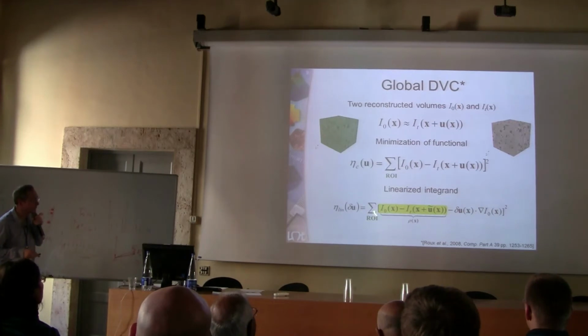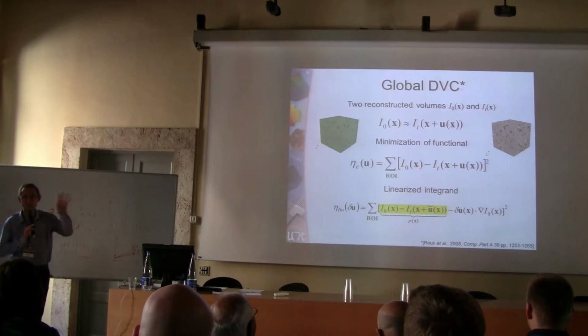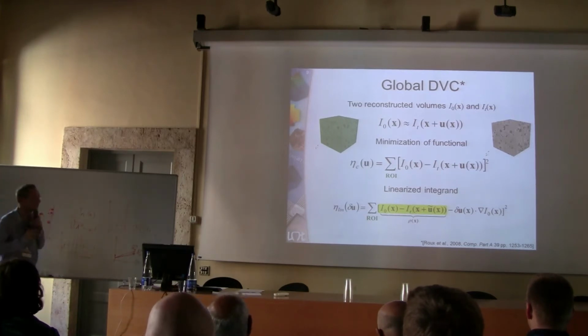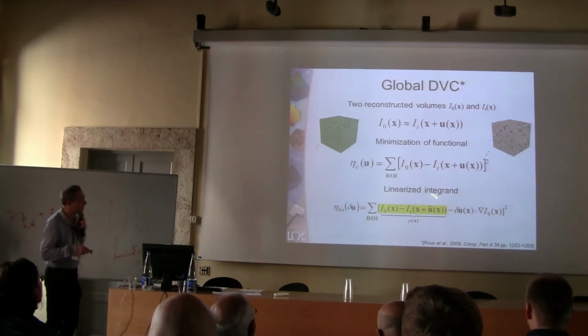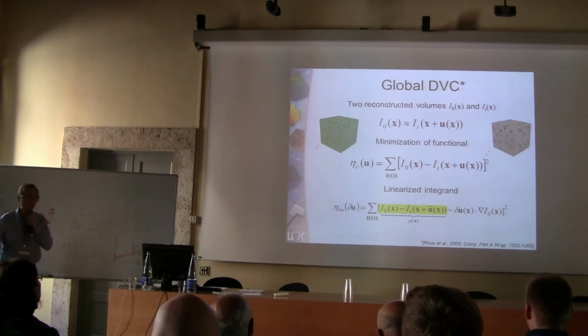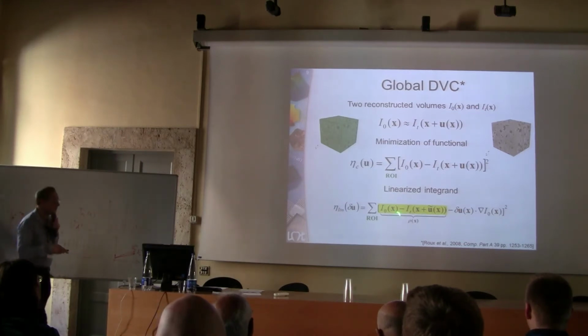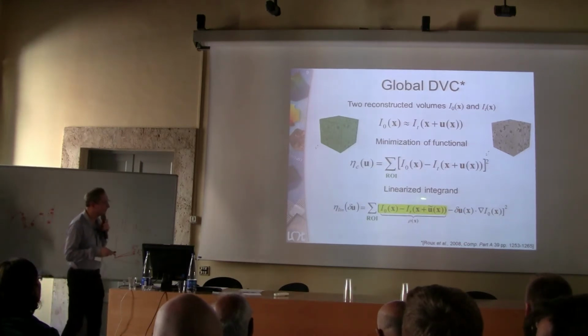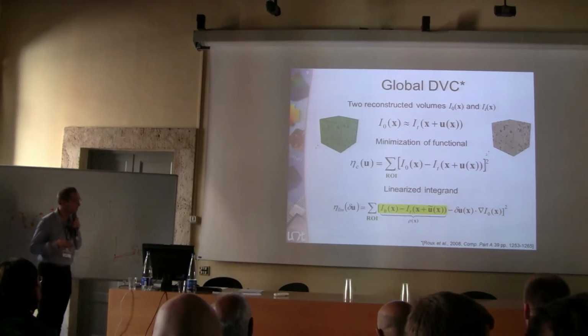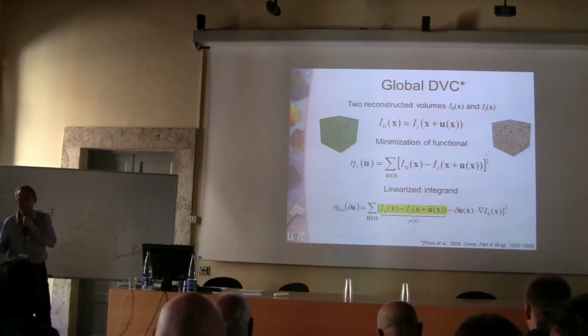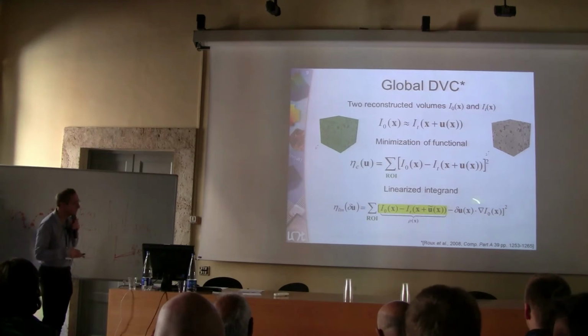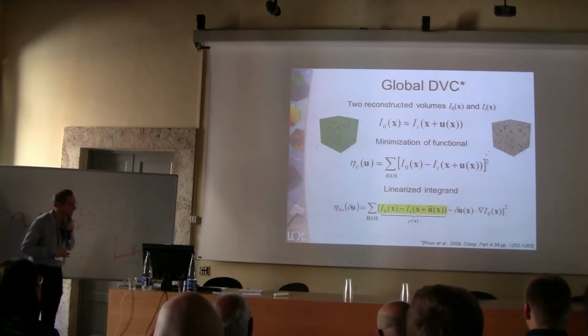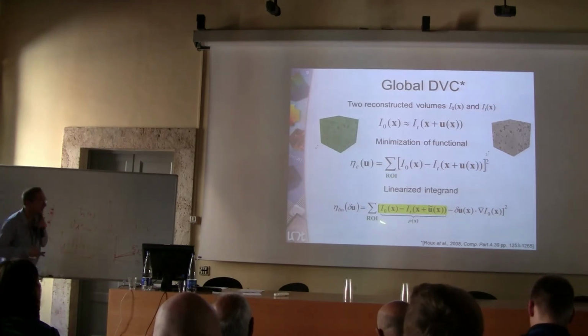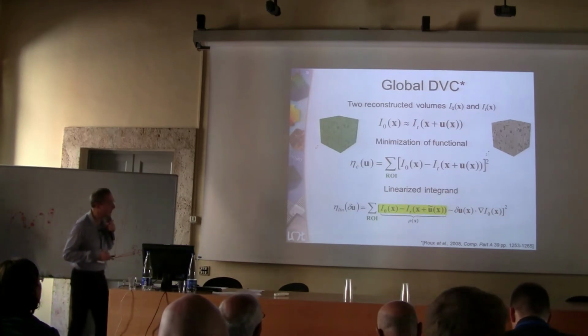What is also important to note is that we started with two volumes, one in the reference configuration, one in the deformed configuration. In the minimization scheme there is a third one, which is the difference between the volume in the reference configuration and the volume in the deformed configuration, corrected by the measured displacement. These are the so-called gray level residuals.